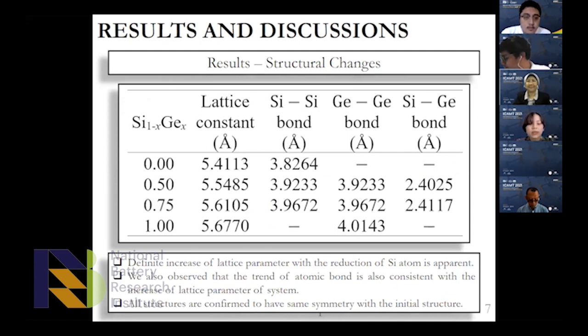So this is our first result, related to the structure change measured for all structures that we calculate in this study. As you can see in this table here, 0 to 1 shows silicon atom composition. In here, 0 defines the pure silicon structure, while 1 defines pure germanium structure. With the reduction of silicon atoms, all structure parameters shown in this table are increasing. This is due to the fact that germanium atoms are slightly larger compared to silicon atoms. And all structures calculated in this study show the same symmetry as one another.